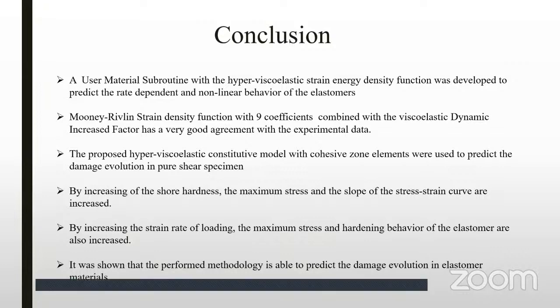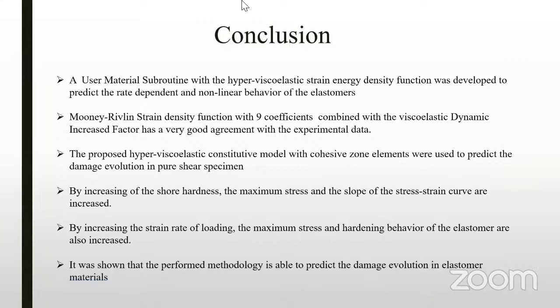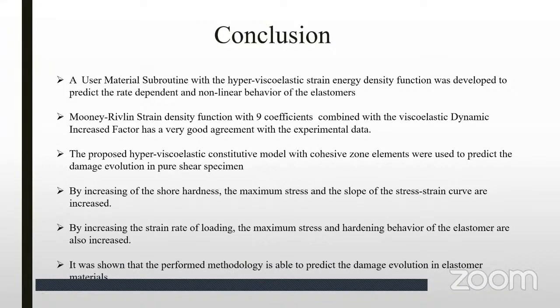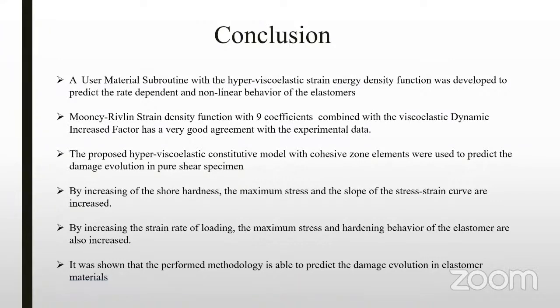By investigating the results more, we can conclude that by increasing the shore hardness, the maximum stress and the slope of the stress-strain curve are increased too. And also by increasing the strain rate of loading, the maximum stress and hardening behavior of the elastomer are increased as well. Overall, we can conclude that the proposed methodology is able to predict the damage evolution in elastomer materials.